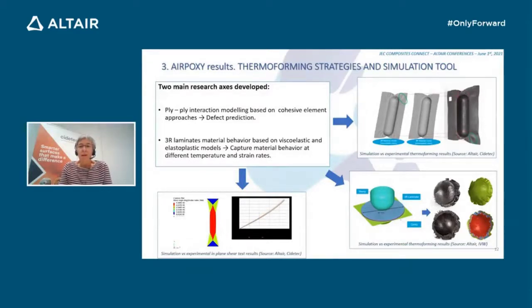The first one is the ply-ply interaction modeling, which is a crucial tool to predict defects, because local wrinkles or delamination can be predicted only if the interface behavior is simulated. It was proved that the cohesive element approach is able to capture the behavior of the 3R resin. In the case of the second modeling, the 3R laminate behavior, a new material model was implemented that on the one hand can capture the material anisotropy during the forming process, and on the other hand can simulate the nonlinear elastic behavior of the fibers and the contribution of the isotropic resin.